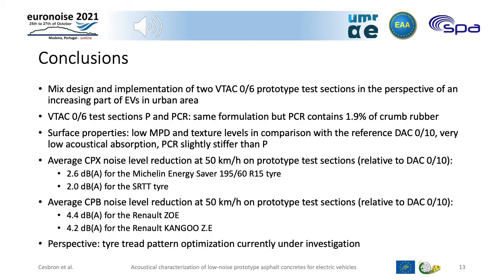Let's turn to the conclusions. In this study, two very thin asphalt concrete 0/6 have been designed and implemented on prototype test sections in the perspective of an increasing part of electric vehicles in the urban area. The very thin asphalt concrete 0/6 test sections P and PCR are based on the same formulation, but PCR contains 1.9% of crumb rubber per weight. Regarding the surface properties, a low MPD and texture levels was observed for both test sections in comparison with the reference dense asphalt concrete 0/10.